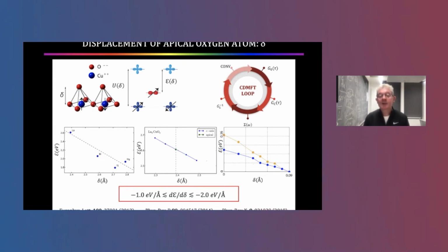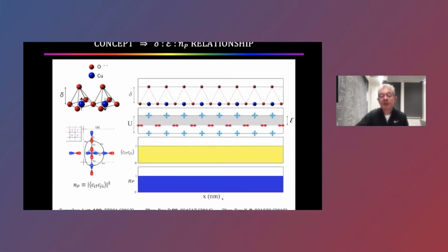Roughly, you get about 1 electron volt of change of charge transfer energy for 1 angstrom of motion of the apical atom. And this concept has been around since the beginning of cuprate research. Move the apical atom, alter the charge transfer energy. So that's the objective. So here's a cartoon now, a little movie showing the concept of our project. So on the top line here, you see the copper-oxygen plane.